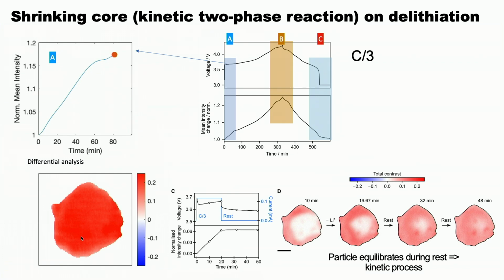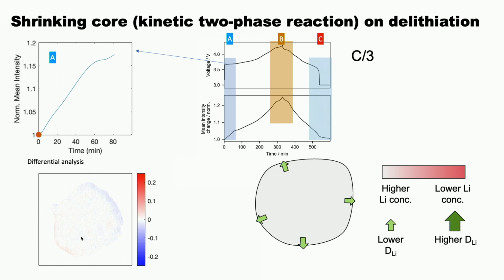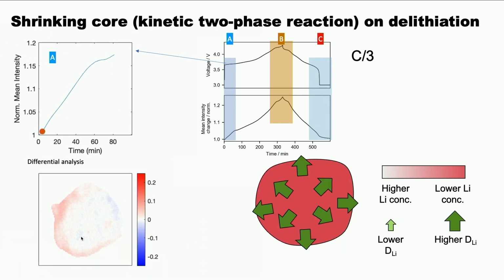But this one is a kinetic process caused by the differences in diffusivity, and I'll show you that in a second. The way to check that is just to stop, let the system relax, and if it relaxes, that indicates it's kinetic. And what's going on is very similar to the lithium cobalt oxide system. You start off with your material, it's stuffed, the lithium's not moving anywhere. You start pulling lithium out from the edges, and again, it's easier to pull it out from the red phase, and so it collapses in a shrinking core mechanism.